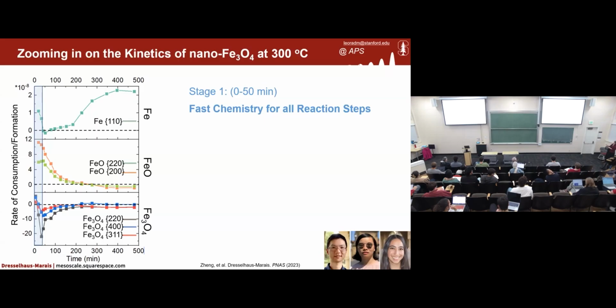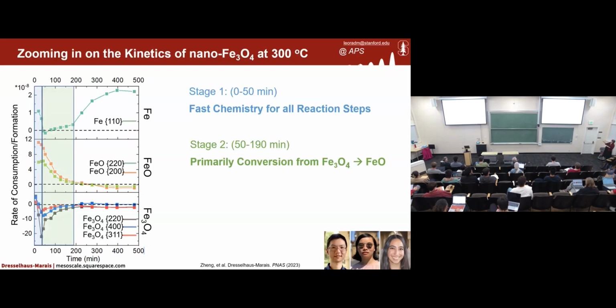So we were able to characterize based on this that in the first stage, for the first 50 minutes, we see fast chemistry for all reaction steps. In the second stage, we see primarily conversion from the magnetite to the wüstite. So that's the first step of the reaction in this case. And in the third stage, we see steady conversion of all the oxide phases to metallic iron.